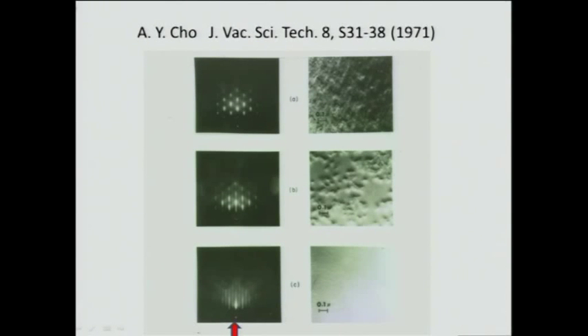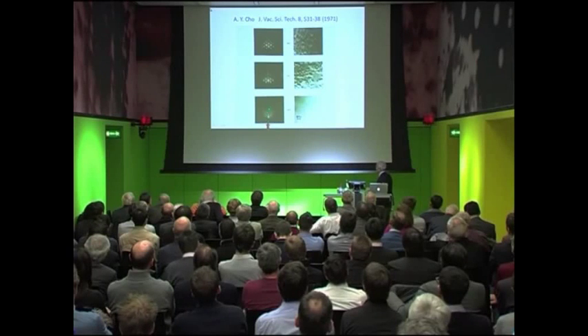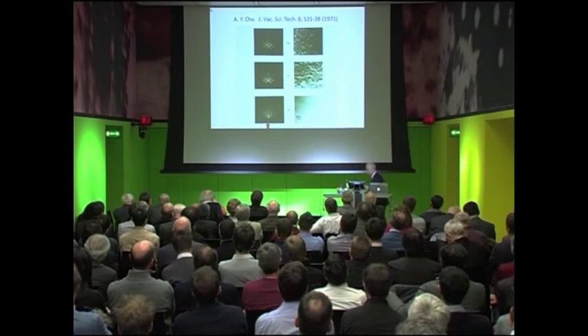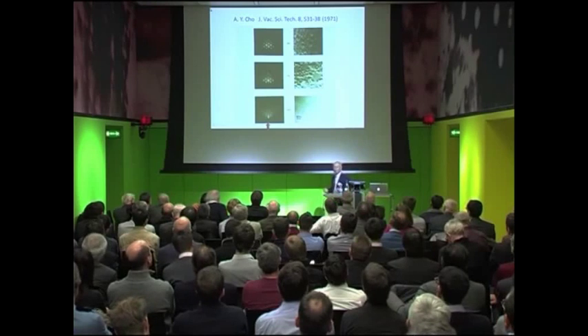As we grow on the surface, we form larger, smoother areas and form an atomically smooth surface with MBE growth. You see here the diffraction pattern becomes streaked. Why does it become streaked? Because the electron diffraction now goes from three-dimensional to two-dimensional, because at a grazing angle it doesn't have these protuberant surfaces of hills and valleys anymore. Therefore, we get two-dimensional electron diffraction. Two-dimensional electron diffraction gives reciprocal rods. The Ewald sphere intersected with reciprocal rods gives us these streak patterns.